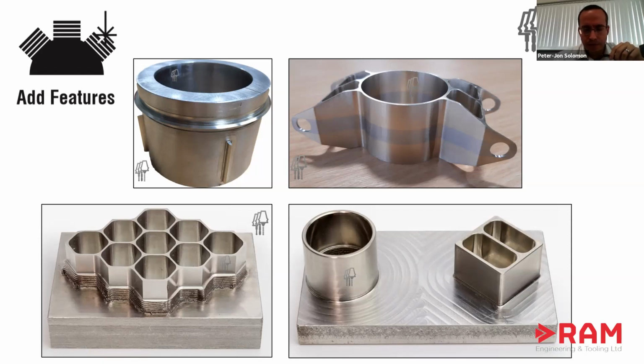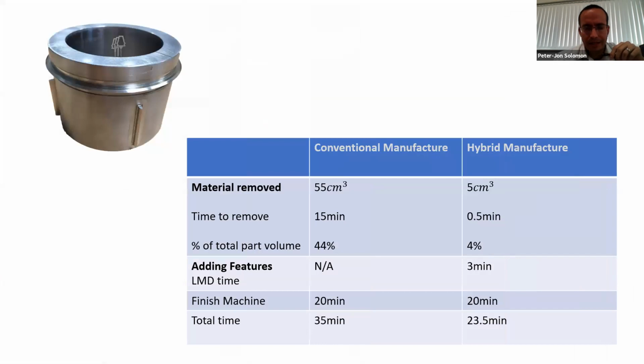Just going over to just look at some of the comparison. If you made that conventionally against hybrid manufacture, if you conventionally machined it, you would have had to start off with a bigger block of material. You would have machined off about 55 cubic centimeters, would have taken about 15 minutes. I mean, you can always argue about what cutters and how quickly you can rough the material off. But essentially that was 44% of your billet would have been machined away.